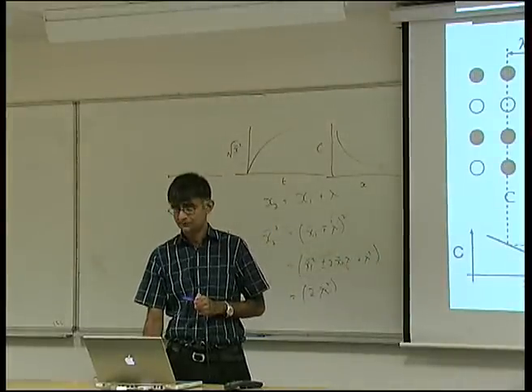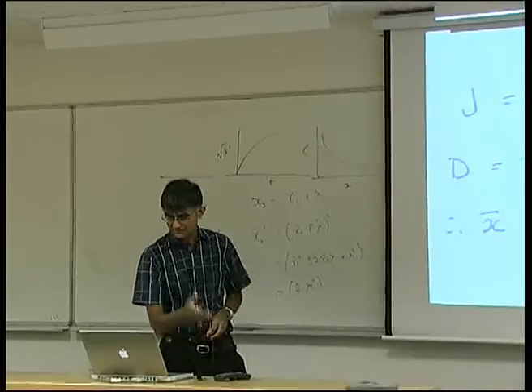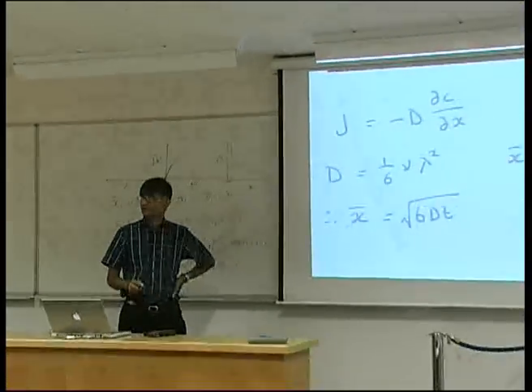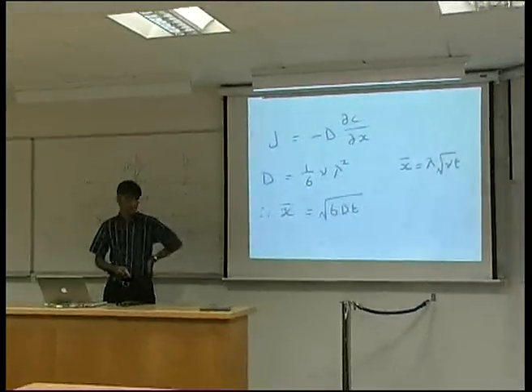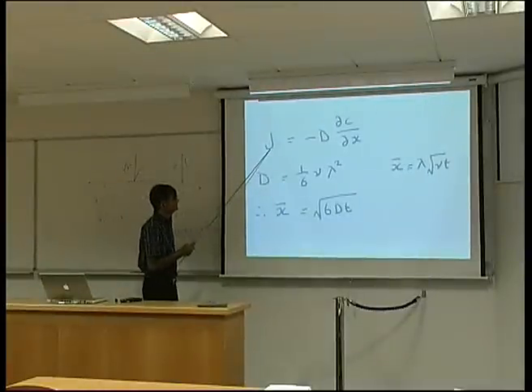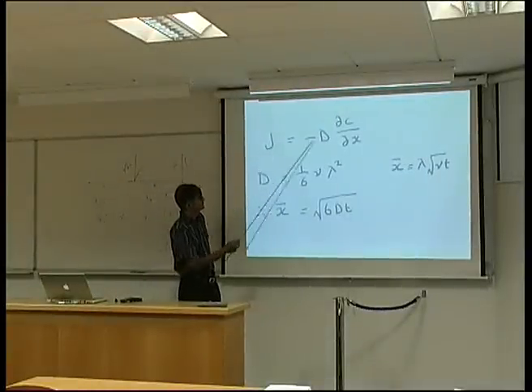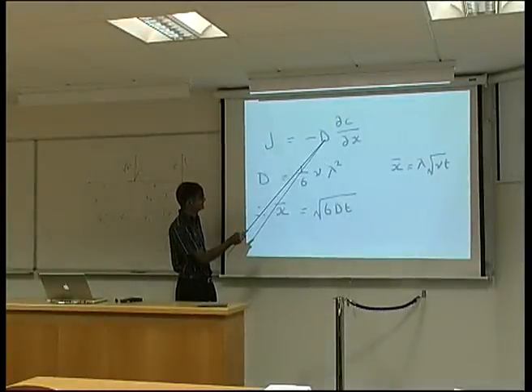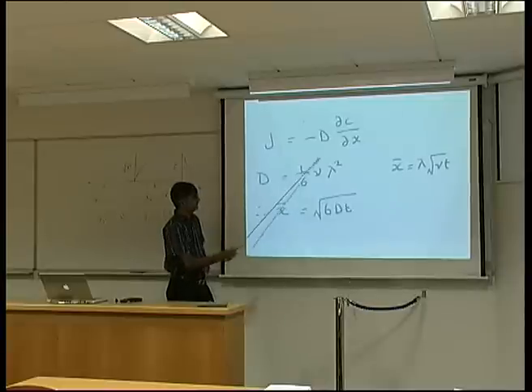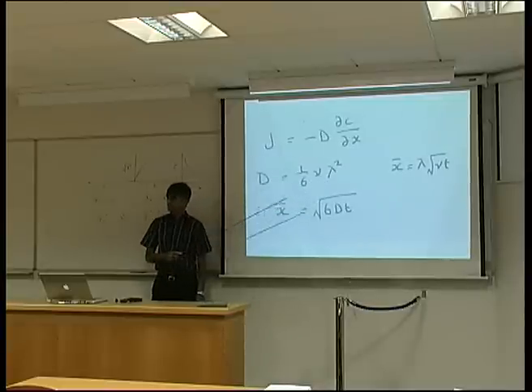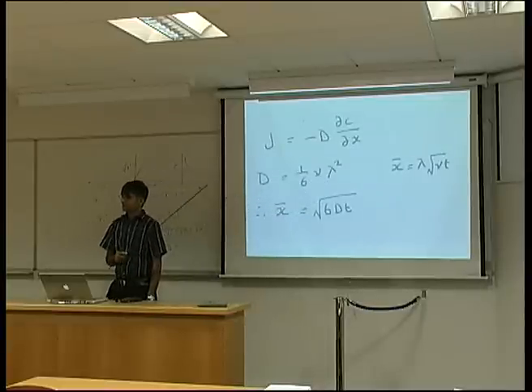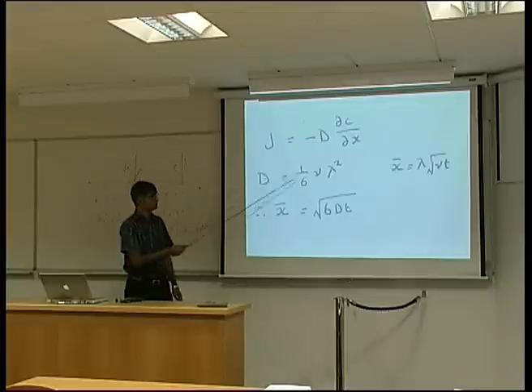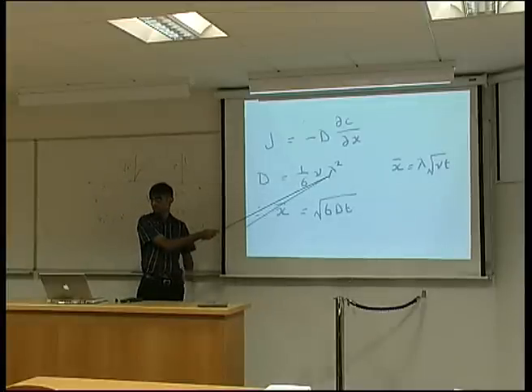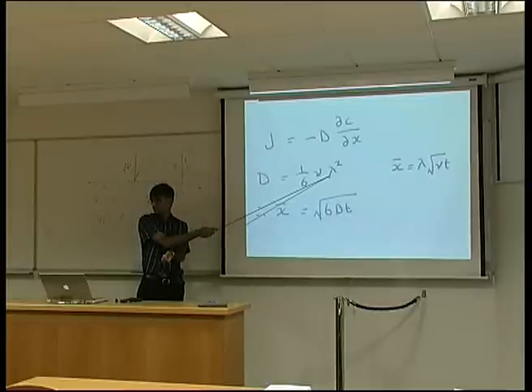Okay, so Fick's first law is straightforward, and we can relate it to that random jump theory that we derived earlier. This is the law: the flux is proportional to the concentration gradient times the diffusion coefficient. We have information which comes from the crystal structure of what the diffusion coefficient is. This is basically the spacing between the planes in the crystal. That's the minimum jump distance.